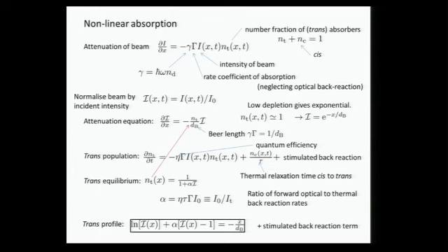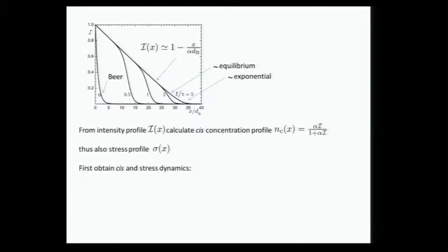And I can then put this into this equation, and it's now a nonlinear equation, and the solution of this equation is this for the intensity as I go through the thickness of this cantilever. And the solution is at short times, when all the dye molecules are present, the absorption is high, and we have this Beer's law. And at long times, right out here, shall we say, the variation is linear. So we have very deep penetration here of the order of 30 or 40 Beer lengths, which in an exponential case would certainly be well zero by that time. And I now have it.